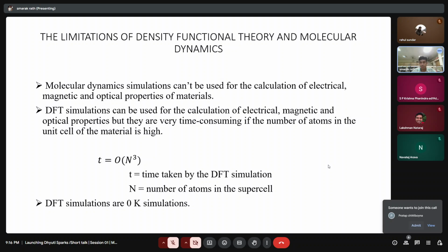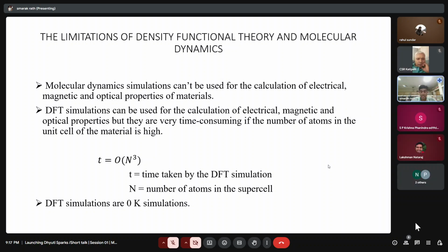Now, DFT simulations are more versatile in that respect because they can be used for the calculation of electrical, magnetic, and optical properties. But the problem is that DFT simulations are much more time consuming. The time taken by a DFT simulation scales as the order of n cube, where n is the number of atoms in the supercell. A supercell is just a term for simulation box. The term simulation box is used in molecular dynamics, and the term supercell is used in DFT. In contrast, the time taken by a molecular dynamics simulation scales as the order of n. So DFT simulations are much more time taking than molecular dynamics simulations, and that's a major drawback.